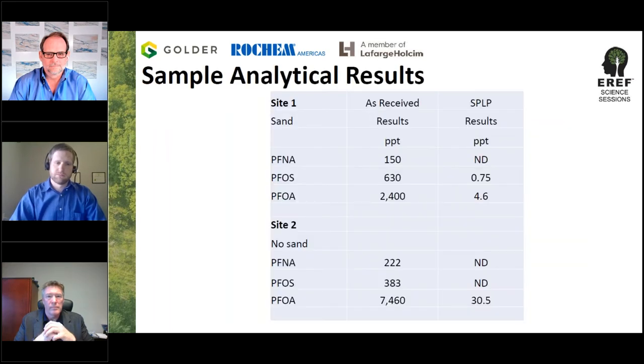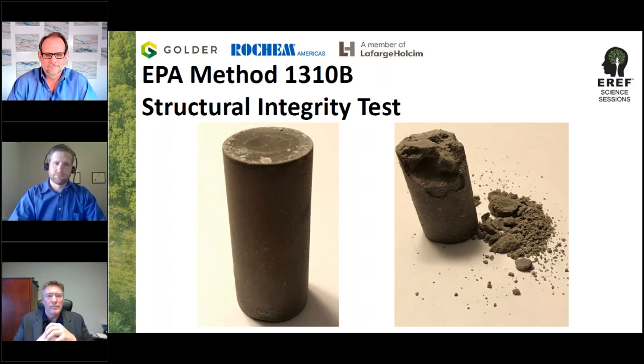And the reason I like this the best is because, would you please go back to that previous slide just for a moment? Because what you have here is a dramatic reduction in surface area. When you have a RO concentrate, you basically have infinite mixing of the pollutants inside of a liquid. But when you solidify it, you've reduced that infinite mixing to almost 91 cubic centimeters on that whole cylinder that you see on the left. Obviously, the system on the right will have a higher surface area. And the only place, I should say, that the extraction fluids from the SPLP extraction method can extract a PFAS out of that system is on the surface. So if you have a whole monolith, like the one on the left, you have grossly reduced the potential for the extraction fluids to extract a PFAS or any other pollutant for that matter. Go ahead to the next.